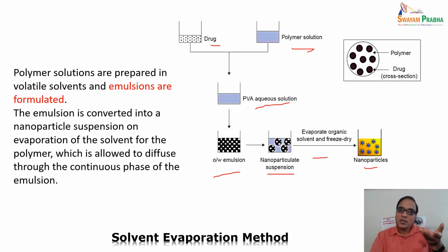So two main strategies we may have: the oil and water emulsification or the multiple emulsion we can prepare, and then with high speed homogenization, ultrasonification, followed by the evaporation of the solvent at room temperature under reduced pressure, the solidified nanoparticle can be collected by ultracentrifugation and washed with distilled water to remove the other additives such as surfactant, finally to produce the lyophilized nanoparticle. This is the simplest method and the most common method used for nanoparticle preparation.